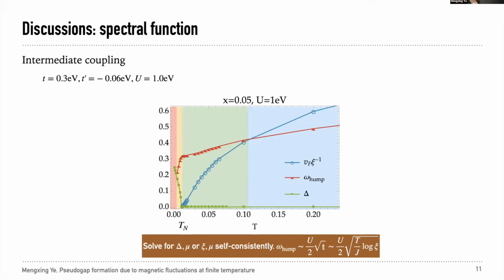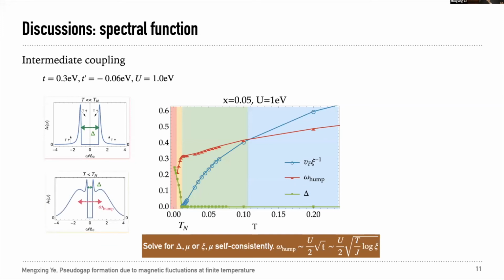Okay, now let me explain in detail how these three energy scales evolve. Let's see what happens when U is about 1 electron volt, in the intermediate coupling regime. From this plot, you can see that at very low temperature, in this red shaded area, the SDW order in green is the largest energy, so that corresponds to this SDW gap in the spectral function. As temperature increases, the hump energy starts to emerge and becomes bigger than the SDW gap. And that's why we can see the two peak feature in the spectral function.